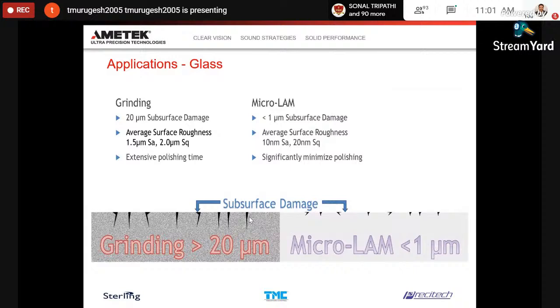subsurface damage. So what do you mean by subsurface damage? Whenever you machine a glass, either you go for grinding or polishing or MRF, for example. MRF is the last process when we talk about polishing. The glass undergoes a stress. It's very much brittle in nature. So what happens is whenever the grinding wheel touches the surface, it creates damage over the surface. That means it produces cracks below the surface, which we call subsurface damage.